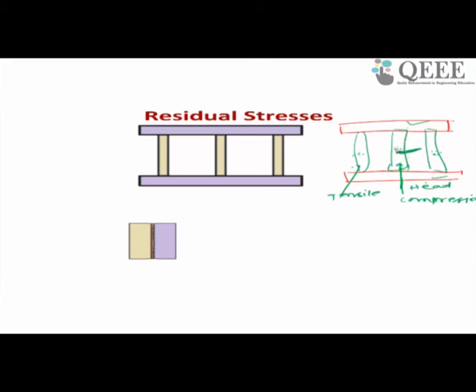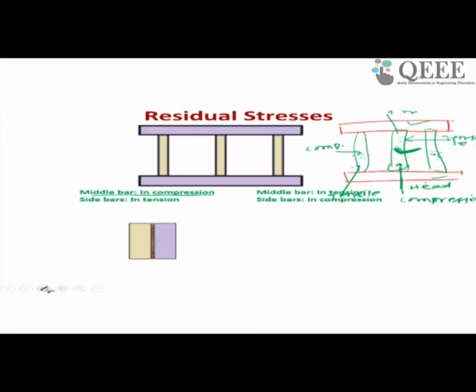Now you cool it. Suppose you have heated this up to just below the melting point of your material. Then you want to cool. During cooling, what will happen? The middle rod will try to contract, and the side rods will not allow it to contract. As a result, after cooling, your middle rod will get tensile stress, and the side rods will get compressive stress. It means before heating, the middle bar is in compression and the side bars in tension. After heating and cooling, the middle bar is in tension and the side bars in compression.